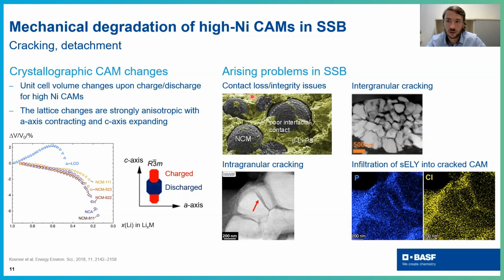There are very nice publications showing the phenomena which are happening in solid state battery during cycling, during lithiation and delithiation. What you can typically observe is, like shown here, detachment of the secondary particle from the solid electrolyte. You can observe intergranular cracking if you make a cross section of your cathode active material, but also you see sometimes intragranular cracking, so that you see that your crystallites really break. And you even observe sometimes infiltration of solid electrolyte into these cracks, which is actually very interesting.